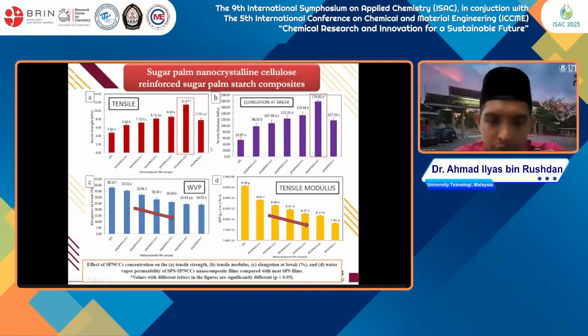There is an effect of reinforcement of the nanocellulose within the starch biopolymer, in which we can see that the tensile mechanical properties were increasing up to 11.47, a 2 times increment of the